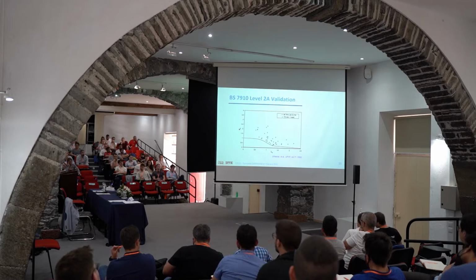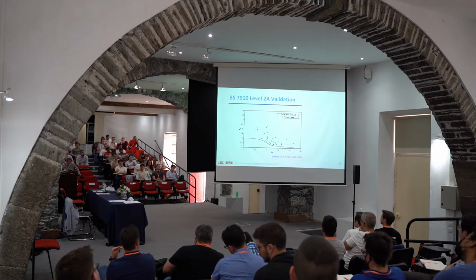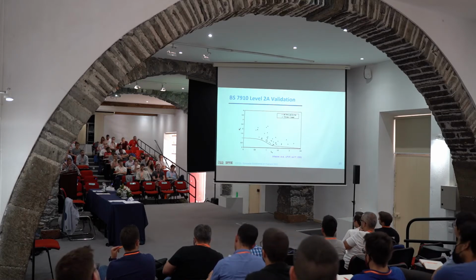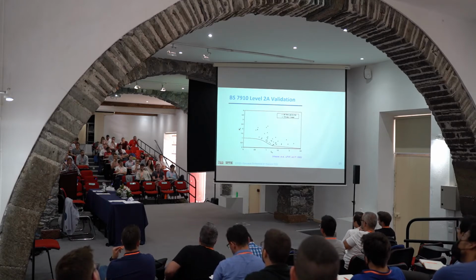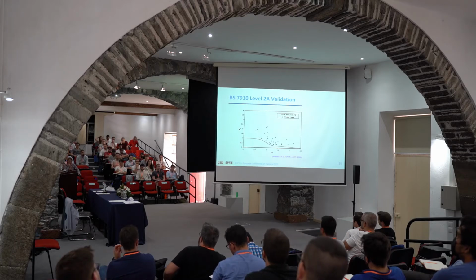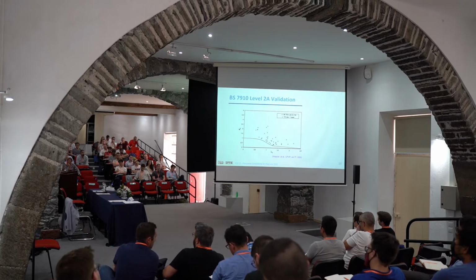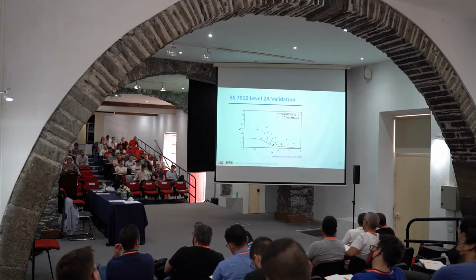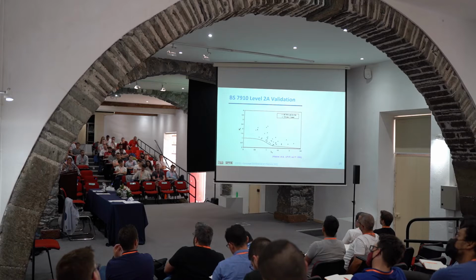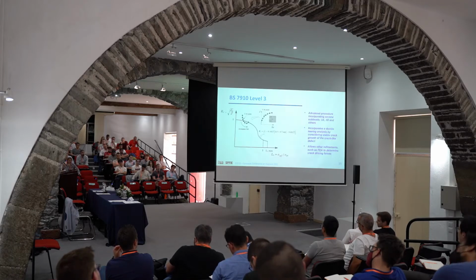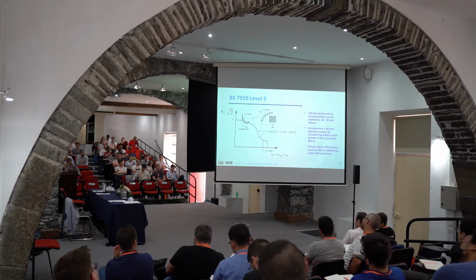So actually, the validation just supports the curve. This curve is a sort of semi-empirical, so it's not an actual mathematical derivation. So we start from the corrective stress fields, from the reference solution. Okay? It's the envelope of the lower bounds of the experiments. Okay? Level 3 is an advanced procedure.